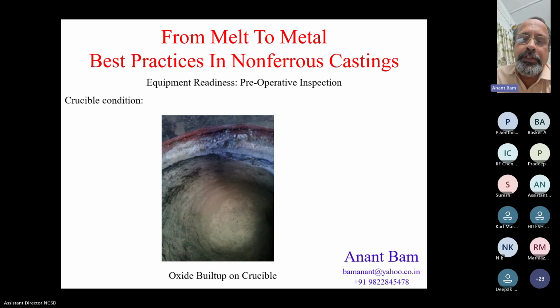So if such a thick oxide lining is present on the crucible, it keeps on dissolving into molten metal, thereby creating oxide inclusions in your casting. That's a serious quality threat. But apart from that, aluminum oxide is a bad conductor of heat, and hence the thermal conductivity of crucible reduces drastically. And hence to melt the metal, you require more and more energy input. That becomes unviable. Next slide, please.